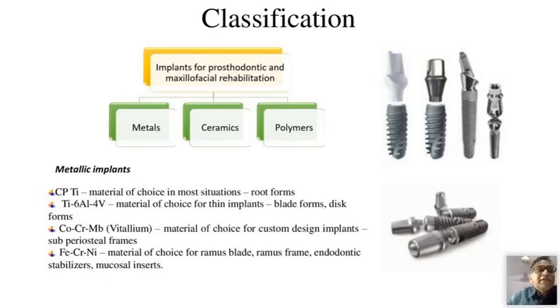And in metals, there can be commercially pure titanium, which has been a material of choice for most of the situations in these root forms, and it started with it, including Nobel Biocare. There are different grades, grade 1, 2, 3, 4 of commercially pure titanium. Each has an advantage and a disadvantage. Then there is titanium grade 5, ASTM grade 5, which is titanium 6 aluminum 4 vanadium, which is a choice for thin implants. That means it has more strength, it has more modulus. It could be in the blade form, it could be in the disc form, or it could be in the threaded form. We have gone in for titanium 6 aluminum 4 vanadium, and not just the grade 5 but also a very advanced grade which is known as extra low interstitial, ELI, which is grade 23 of ASTM, because we wanted to have the minimum diameter of the implant to the maximum diameter of the implant of the same type.